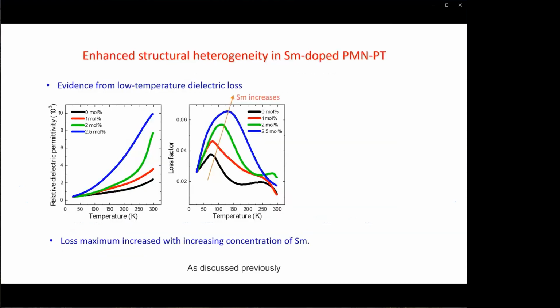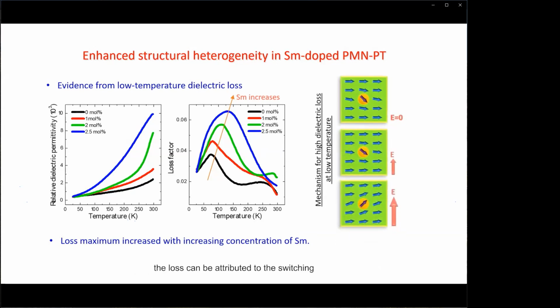As discussed previously, we think that the high piezoelectricity is associated with the enhanced local structure heterogeneity in samarium doped PMN-PT. We have 2 pieces of evidence for the enhanced structure heterogeneity. First is the low temperature dielectric behavior. We can see that the dielectric loss maximum is increased with increasing concentration of samarium. Compared to phase field simulations, the loss can be attributed to the switching of heterogeneous polar nanoregions, as shown here.